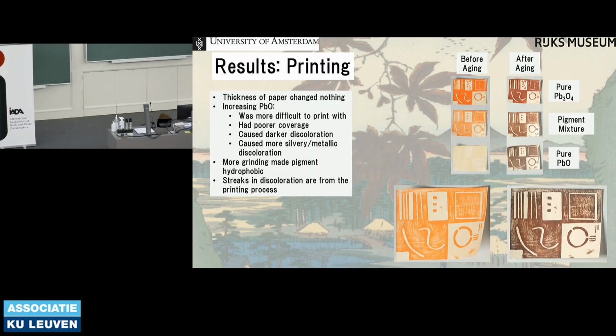While printing the reconstruction, I found that the thickness of the paper did not have an effect on the quality of the print, and in fact did not have significance on any part of the printing, and I will not be mentioning it further. In contrast, the ratio of red lead to lead monoxide was hugely significant and affected every element of the print. Generally, the more red lead that was in a sample, the easier it was to produce an even and consistent print with no lines left behind by the printing brush. In contrast, lead monoxide was very difficult to print with. It did not mix well with water or paste and often printed very thinly and in clumps, no matter how much it was manipulated. Here you can see that there's a decreasing amount of coverage as the amount of red lead decreases and the amount of lead monoxide increases.